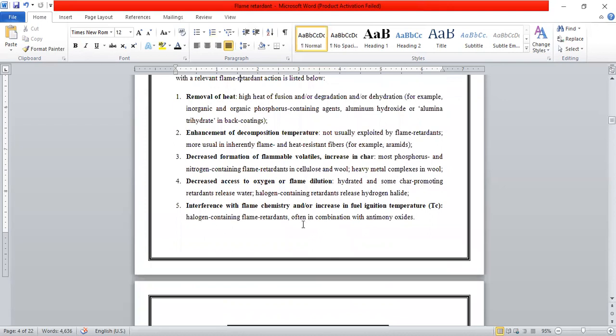First one is removal of heat. High heat of volatilization and/or degradation or dehydration, for example, inorganic and organic phosphorus containing agents, aluminum hydroxide or alumina trihydrate in back coatings. Enhancement of decomposition temperature, not usually exploited by flame retardants, more usual in inherently flame and heat resistant fibers, for example, aramids. Decreased formation of flammable volatiles and increase in char, as with most phosphorus and nitrogen containing flame retardants in cellulose and wool, and heavy metal complexes in wool.